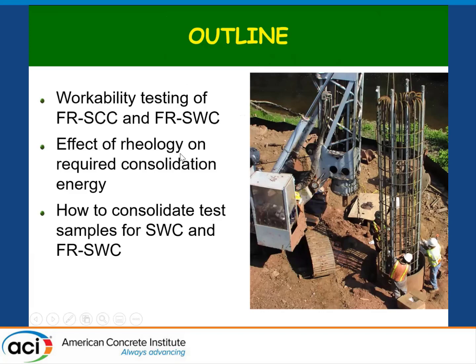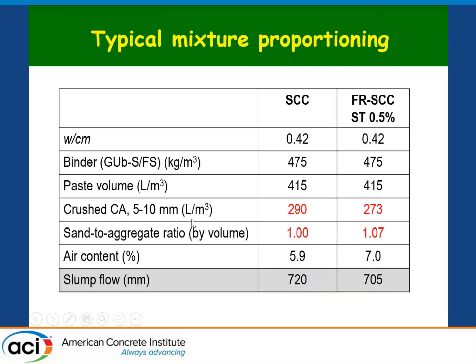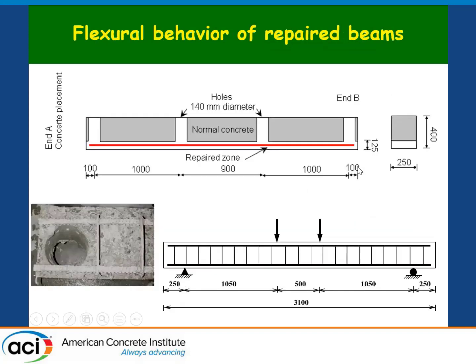The first one, what are the modifications of workability test methods? And here I'm presenting a typical mixed design for an SCC and a typical mixed design of an SCC with 0.5% fibers. These are short fibers, 1.5 inches, 38 millimeter. And you can see in the mixture proportion, the only thing that has changed really is the sand to aggregate ratio and the crushed coarse aggregate content. Otherwise, the binder and water binder is the same.